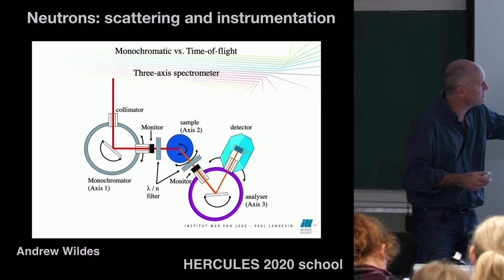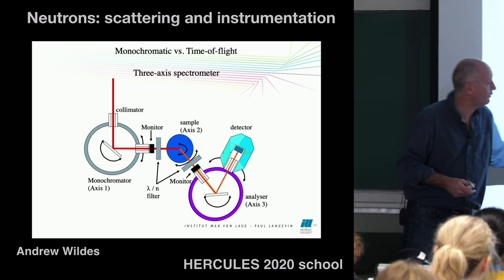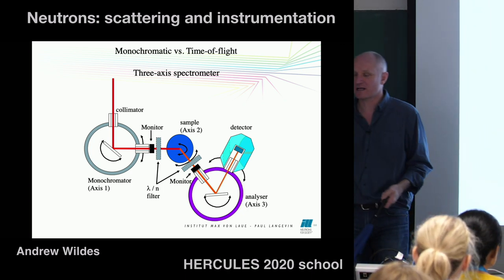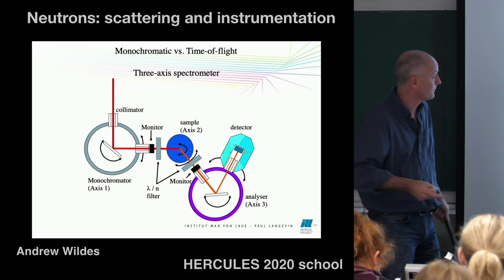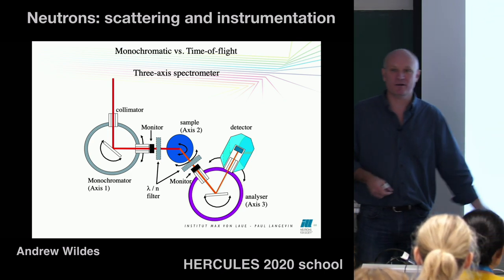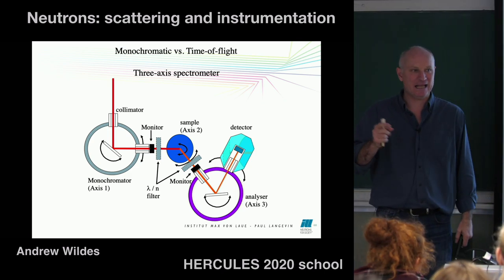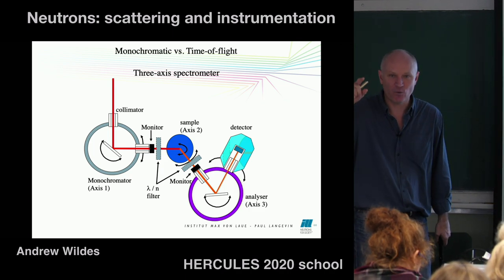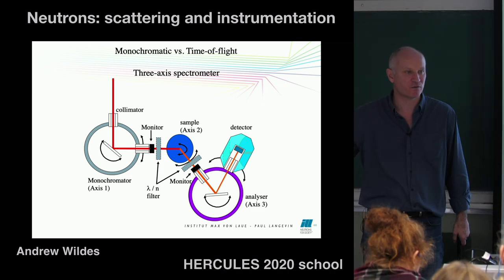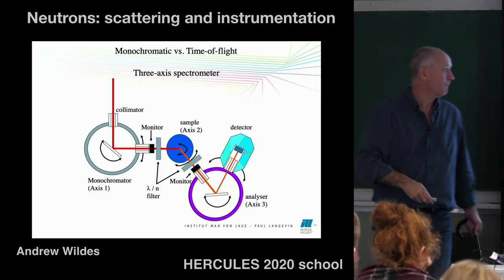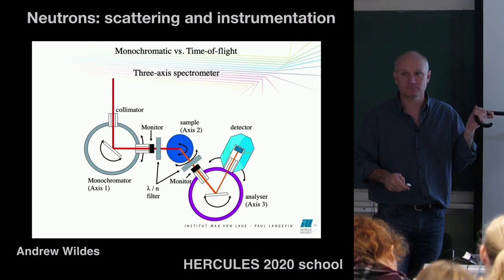You've chosen an incident wavelength, you've chosen a final wavelength, and you've got the rotation of your sample to give you a momentum transfer. So what you're doing with this instrument is you're measuring one position in Q, momentum transfer, and one energy transfer, one point only. But you get a lot of intensity at that point.